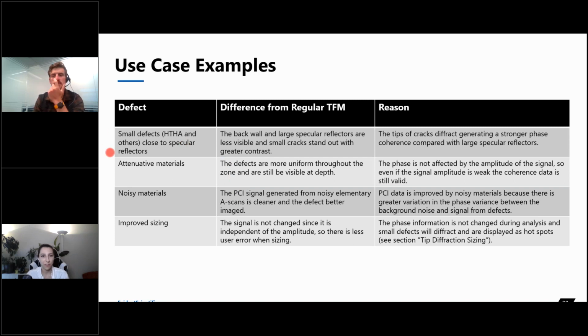Okay, so for small defects, especially we've realized, so for HTHA, also creep damage, something that is very close to a specular small reflector, in comparison to a regular TFM, we've noticed, as we mentioned before, that the back wall and large specular reflectors are less visible, and then small cracks will stand out much more. So the back wall will be less loud, and then the very small defects or bubbles or intergranular cracks will appear very, very nicely. The reason for that is, again, the tip of the cracks diffract the energy, and that generates a very strong phase coherence in comparison to the large specular reflectors that are close to it.